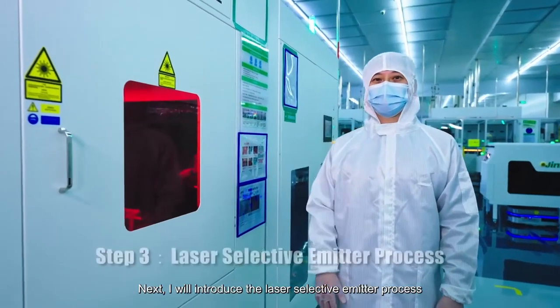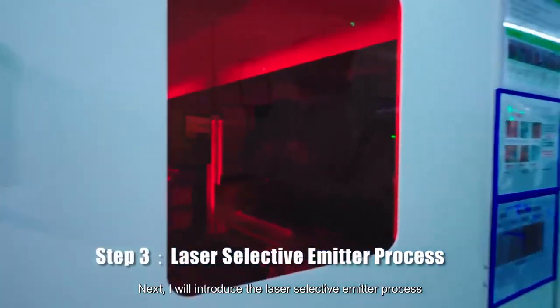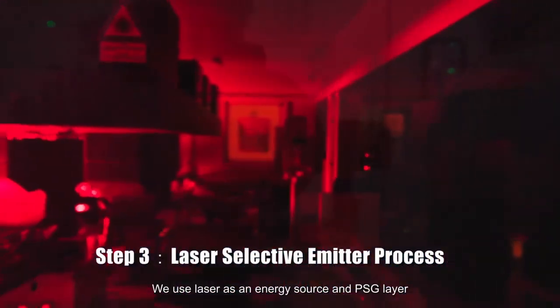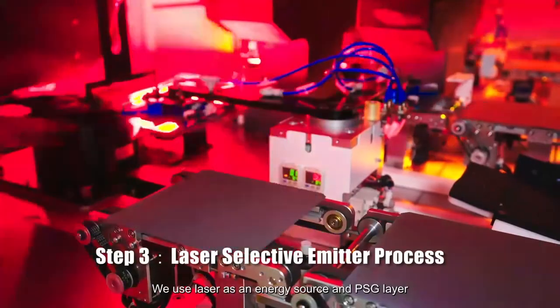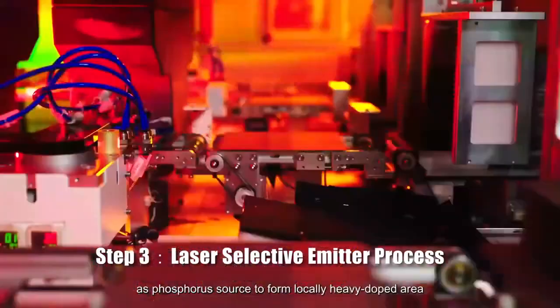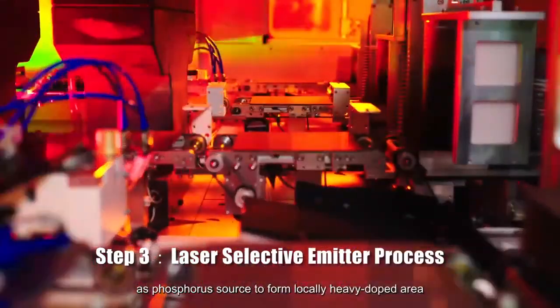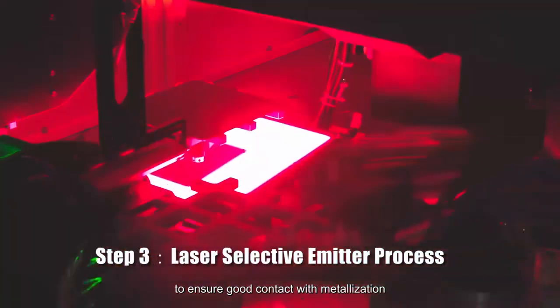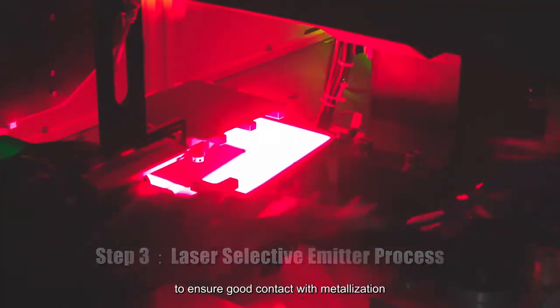Next, I will introduce the laser selective emitter process. We use laser as an energy source and the PSG layer as phosphorus source to form a locally heavily doped area to ensure good contact with metallization.